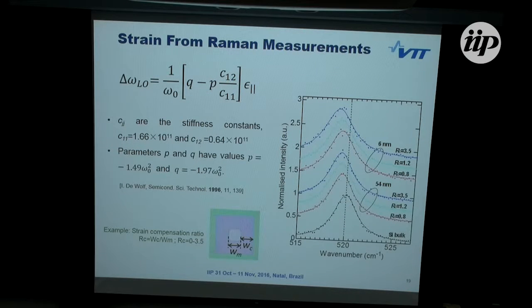So here's an example of Raman measurements from a different set of samples. So this is now the 520 wave number peak, and this is the bulk silicon, so this is a reference. And then there are three different membranes with a thickness of 54 nanometers, and then three different samples with a thickness of 6 nanometers.